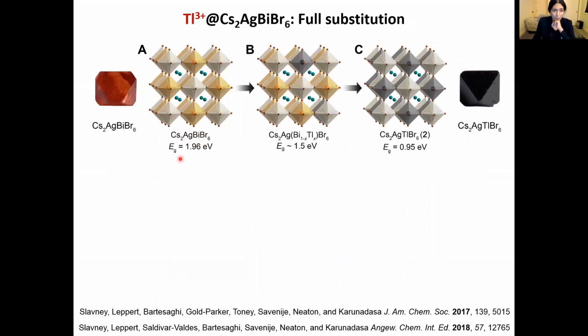So the band gap is too large, and the band gap, if you remember, was indirect, so it was absorbing sunlight weakly. And using the principles that I outlined, we can show that if you add just a little bit of thallium 3+ into the bismuth 3+ site, so less than 1 atom% of thallium in the material, we can drive down this band gap to close to the ideal band gap that we want for a single junction solar absorber.